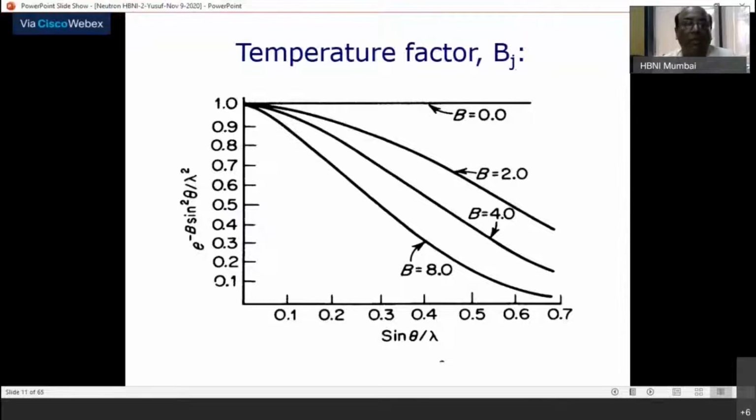So that is not the case. Even at t equal to absolute 0, you might see the quantum effect. But of course, it is needless to say that if you do an experiment at much higher temperature, then this factor will be more. Or if you have a sample where lighter atoms are there, they are more likely to be oscillating with a larger amplitude with respect to their mean position. For example, oxygen can have larger B. In fact, indeed it is so. In most oxides, let us say tungsten metal oxides, you see for oxygen, B is much larger than the metal atoms, because metal atoms are heavier. That is in general so.